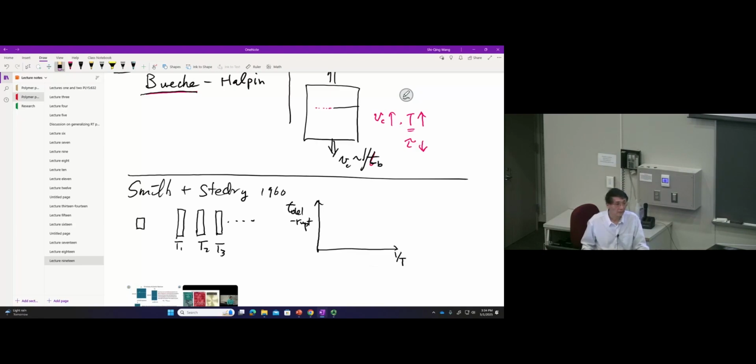So why is this a beautiful experiment? You stretch without a cut either. You stretch and hold. All the relaxation is gone. Nothing is moving, and you just wait. There's no way you can invoke any viscoelasticity in the problem.